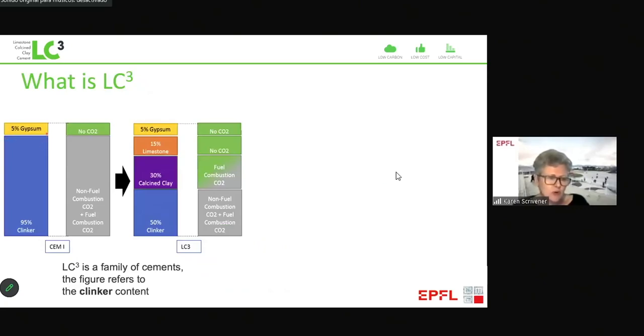So essentially what we're doing with LC3, we're replacing a large part of this clinker, which is what produces the CO2 emissions, by a combination of calcined clay, which has some emissions from the calcination, but these are much, much lower than clinker, up to 10 times lower, and limestone, which essentially has no CO2 emissions. So this is the mix we call LC3-50. This means it has 50% clinker content, but in some applications you can even go to lower clinker contents of at least 40, down to 40% or maybe even lower.